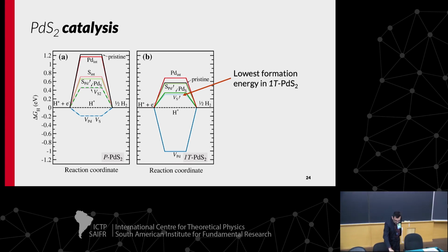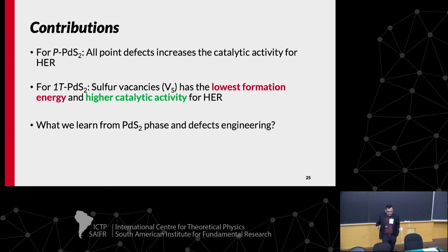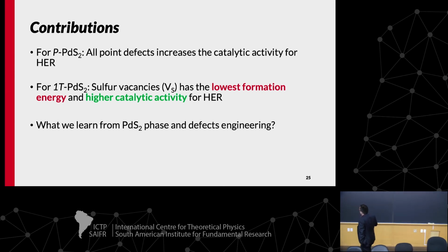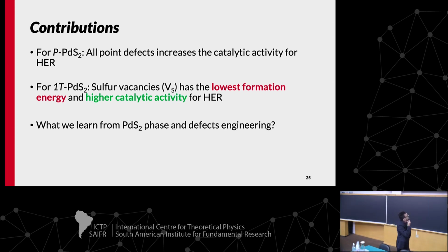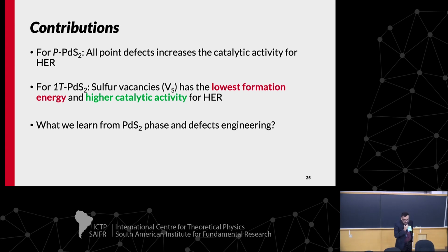So in this case, I need to talk about some contributions we did. This paper was also published by this PhD student. We have all the defect effects increasing the catalytic activity for the hydrogen production reaction. For the sulfur vacancy, I need to highlight two things: it has the lowest formation energy, so it's the more common defect, and it has higher catalytic activity for the hydrogen evolution reaction.